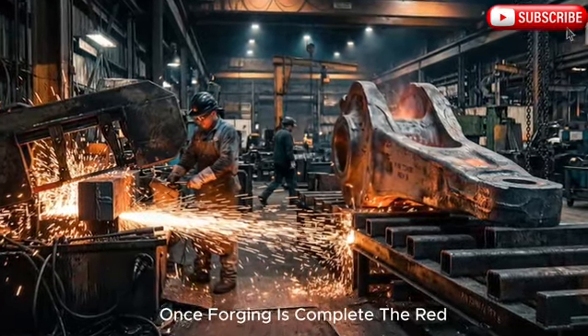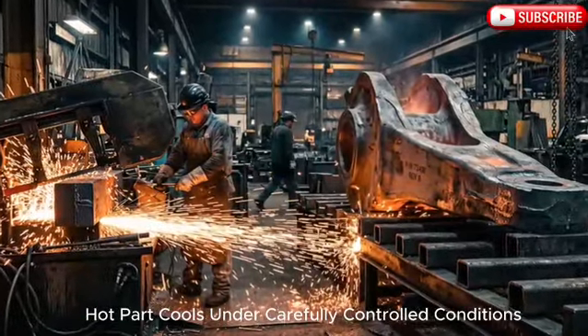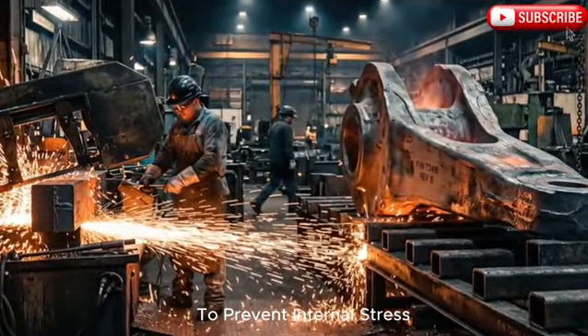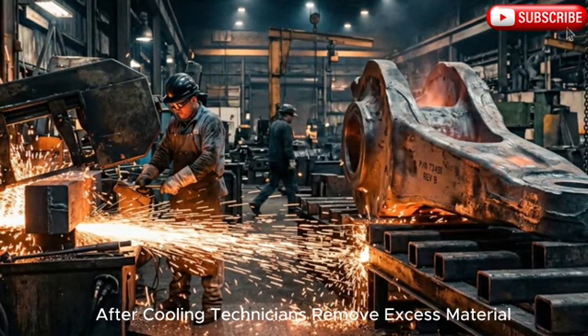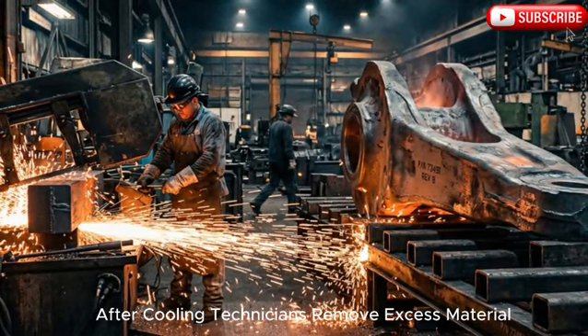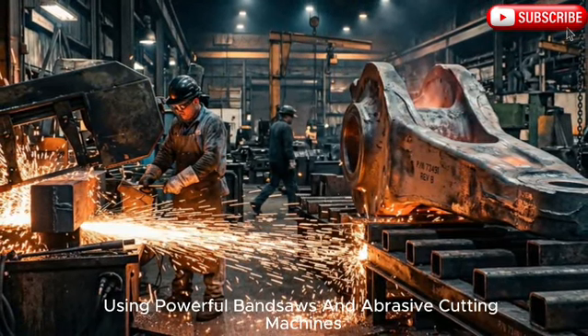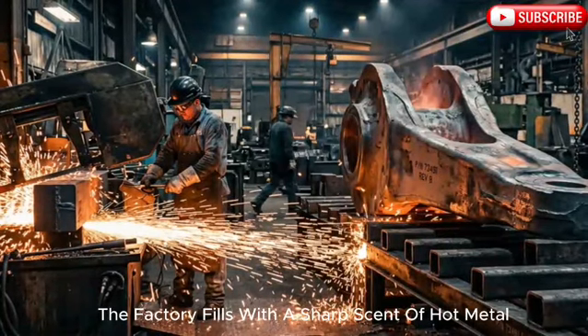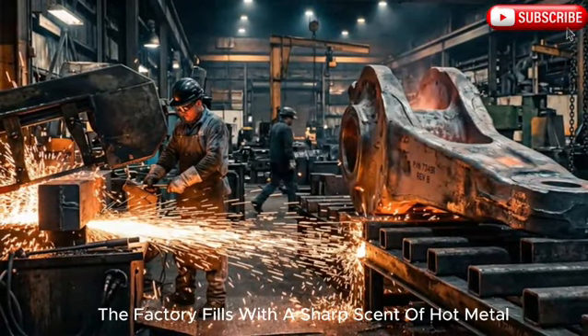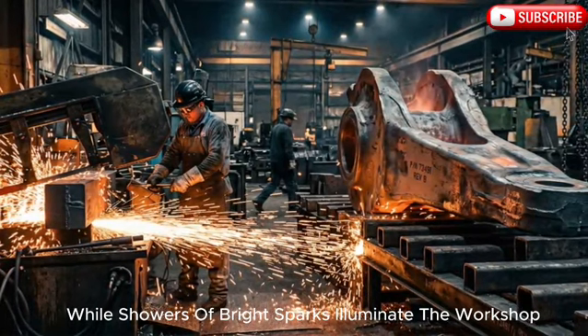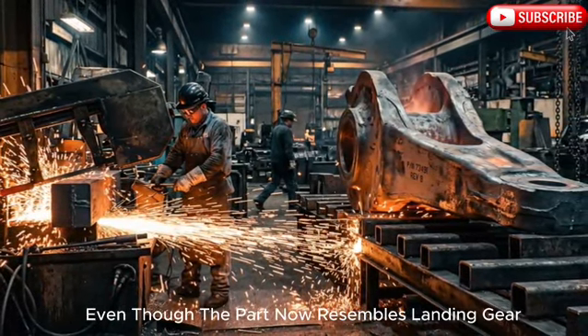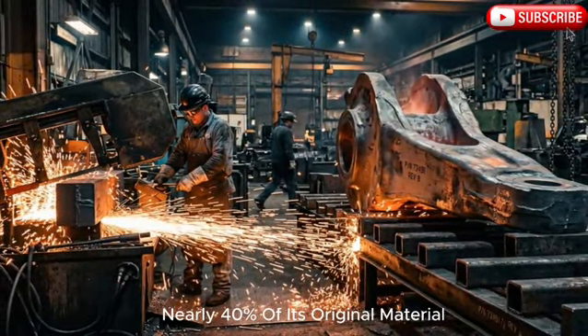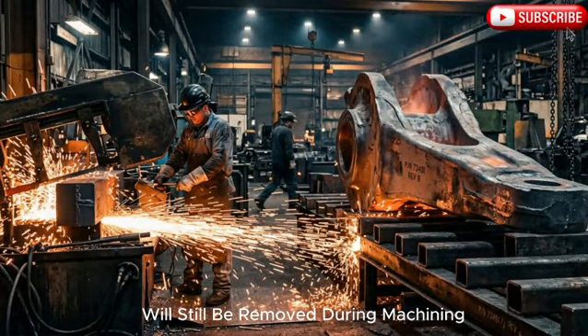Once forging is complete, the red-hot part cools under carefully controlled conditions to prevent internal stress. After cooling, technicians remove excess material using powerful bandsaws and abrasive cutting machines. The factory fills with a sharp scent of hot metal while showers of bright sparks illuminate the workshop. Even though the part now resembles landing gear, nearly 40% of its original material will still be removed during machining.